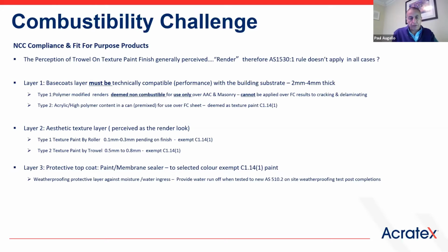The last part, the protection layer, layer number 3, has another critical aspect, and we've learnt this here in Victoria through the CSV requirements, where they're doing water runoff tests in relation to weatherproofing, on how much water is absorbed onto the surface post completion on the job site before the surveyors sign off. That standard put up by the CSV is very easily done and observed on site, because where you don't have that protective layer, the texture layer will absorb the water or moisture in, whereas with that layer over the top, the water will just run off it like it runs off your car, it'll just bead off.